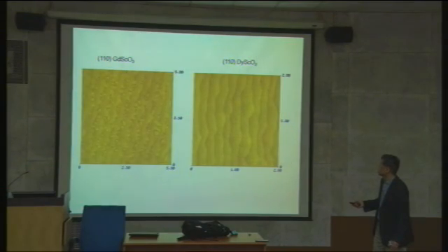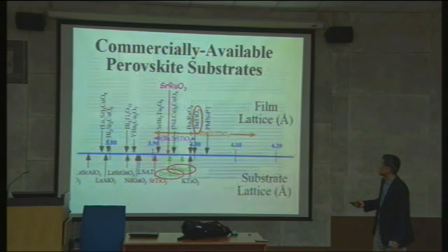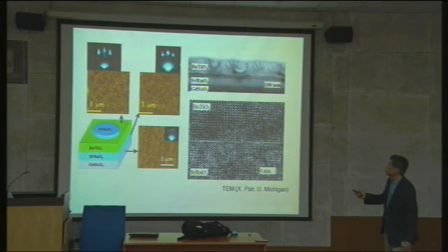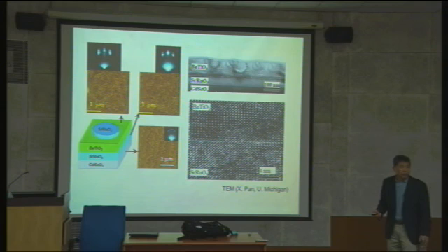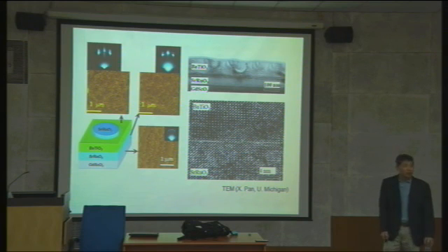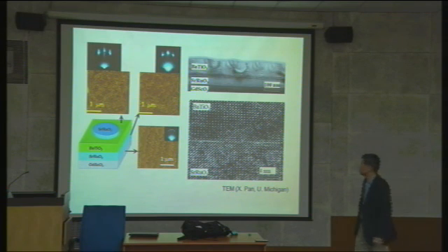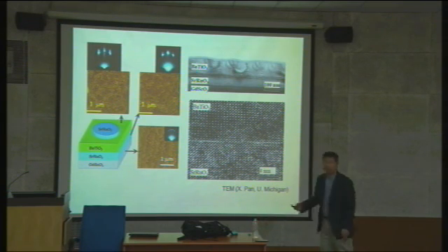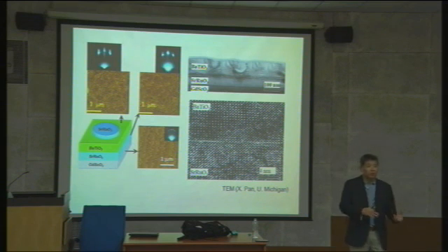So let me just go here. When you look at the barium titanate, you look at the surface, strontium titanate and barium titanate, we have no dislocation. You have dislocation lines here usually, and then it's fully coherent and absolutely no dislocation. And this is consistent with the actual lattice parameter measurement by X-ray diffractometer. Okay? So I'm going to stop it here, and then this strain fundamental epitaxy.